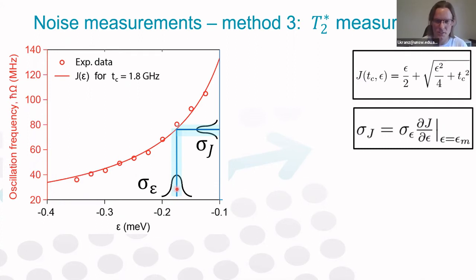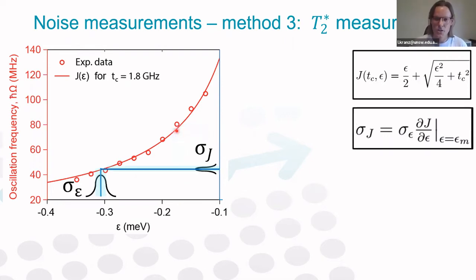So if you set voltages to a certain detuning position, you will actually have a distribution of your detuning values, because of the intrinsic noise in the device that shakes the electrochemical potential. So for now, let's assume it's a Gaussian distribution of values, and therefore you will not get a single value of J, but you will actually also get a distribution of J values. And this mapping between distribution of detuning and J values can be described by this equation here. You basically have to take into account the derivative dJ/dε. So what this means basically is that for a given detuning noise, if you go to lower detunings, you will get smaller J noise because at this point your dJ/dε is smaller. This function is less steep.